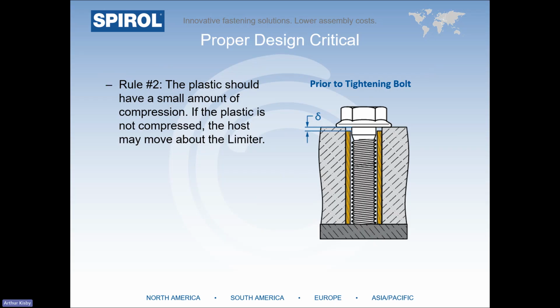Rule number two is the plastic should have a small amount of compression. If the plastic is not compressed, the host component may move about the limiter. By the way, it's important to note that the delta showing in the gap in this image that you're seeing on the screen is only there prior to the torquing down of the bolt. Once the bolt is actually tightened down, the plastic needs to be compressed to get that metal on metal contact Sean was just mentioning. That is really just a non-negotiable.